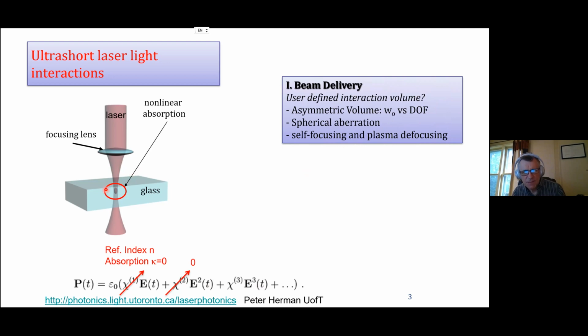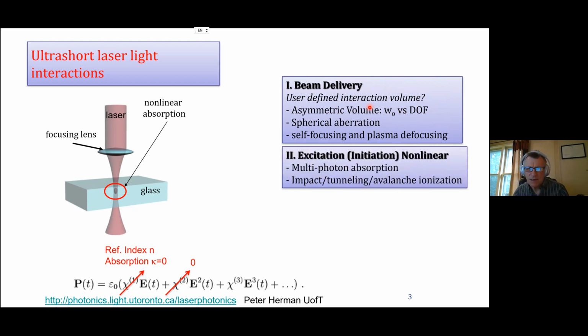And when you focus into material, you also have spherical aberrations, which can really distort the beam. So from a Gaussian profile with a minimum spot size and a small depth of focus, lots of unusual propagation effects will take place. And while you're interacting with the material, it's changing. Once you absorb, it's not the same material, and that provides a feedback back to the beam propagation, which can really distort the dissipation volume. Now that is how light gets in.